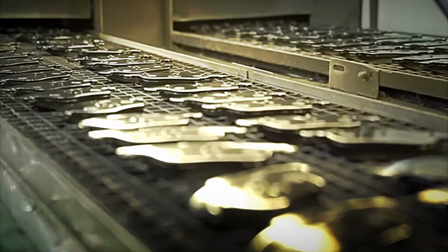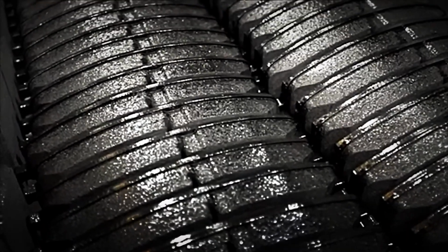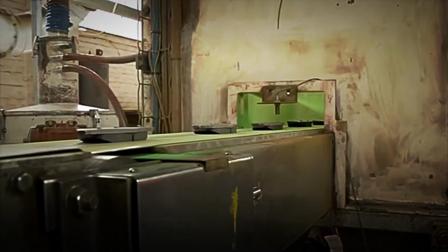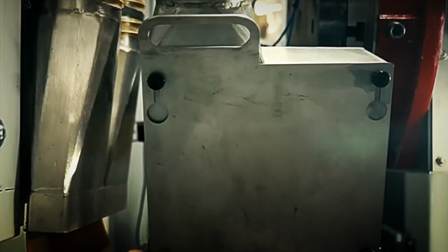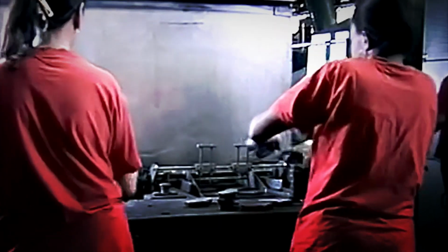be impossible to correct. Pressing is one of the most demanding moments of the process. The press applies enormous forces, on the order of tens of tons, and generates extremely high pressures on the mixture. In a matter of seconds, the moist mass is compacted, the trapped air is expelled, and the particles move closer together until they form a solid block. This extreme pressure not only gives shape, but also creates a high internal density, essential for the pad to withstand both temperature and pressure during braking.